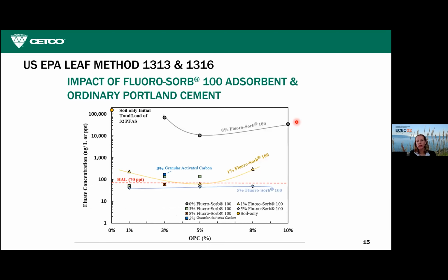I just want to make one comment about soil stabilization. Fluorosorb can be used to stabilize PFAS in soil. This plot is showing the reduction in leaching of PFAS from soil for a 5% mix of Fluoro-Sorb 100 and ordinary Portland cement. You can see that it was able to reduce the leaching beneath the EPA health advisory limit as compared to 0% Fluorosorb. And we also have a full-scale application for soil stabilization of PFAS with Fluorosorb.